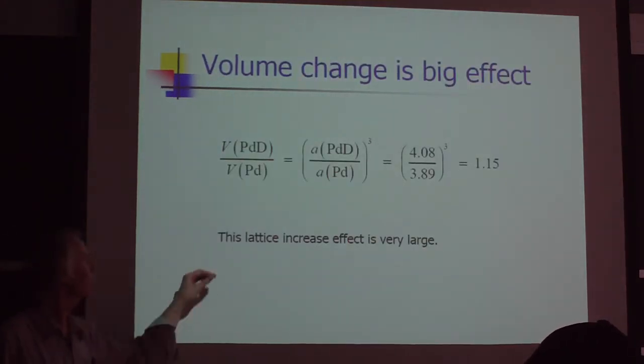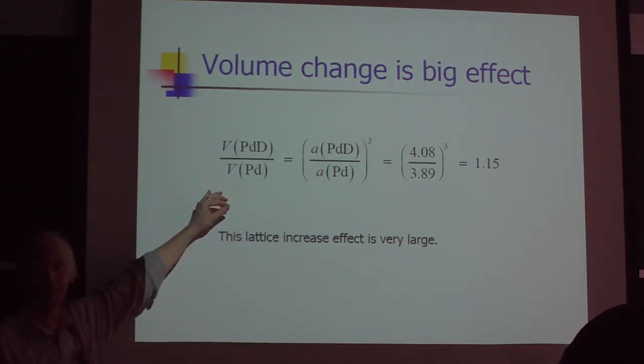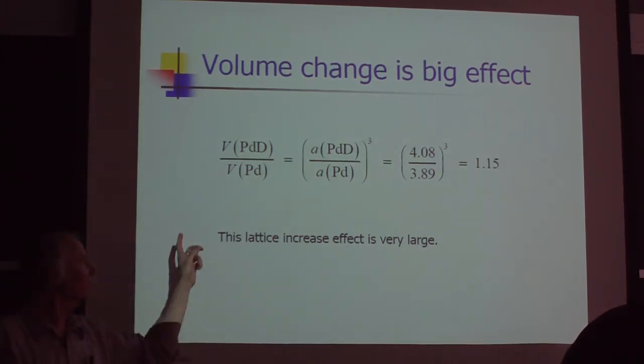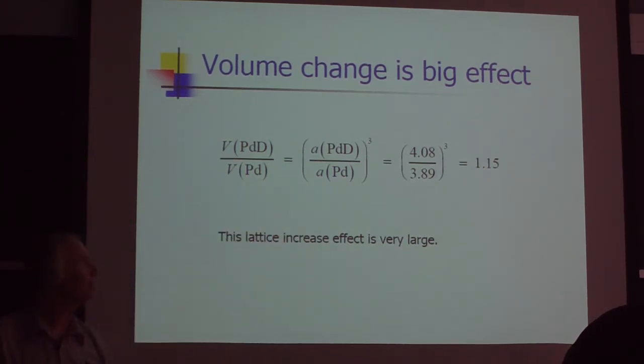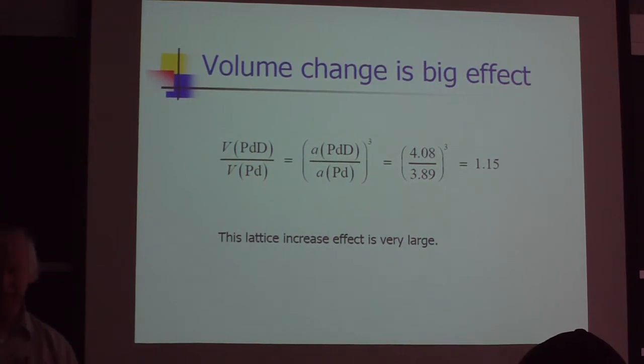So the volume of the palladium deuteride is larger than the volume of the palladium. When you put the deuterium or hydrogen in, the lattice expands. It stretches it out. And for fully loaded palladium against basic palladium, it's a factor of 1.15. It's like a 15% increase in volume. That's actually a huge effect.